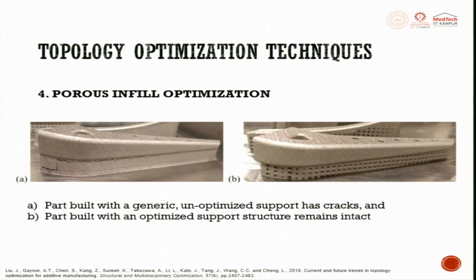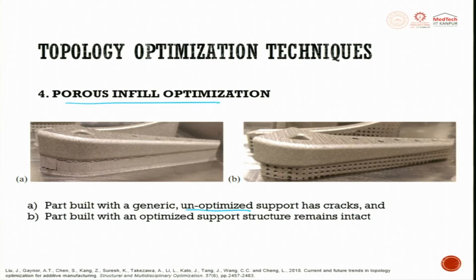In porous infill optimization: a part built with generic unoptimized supports develops cracks due to the unoptimized support. When porous infill optimization is applied, the porosity enables better heat exchange, reducing residual stresses, so no cracks form and the part built with optimized support structure remains intact.